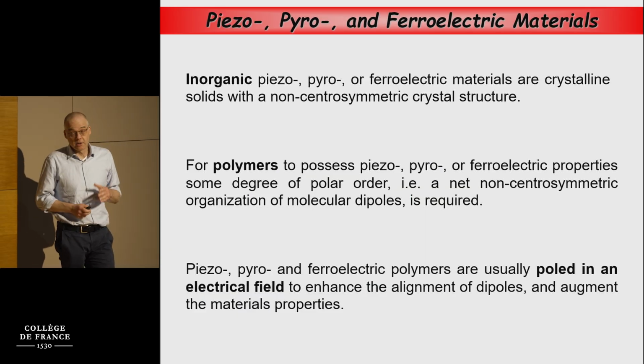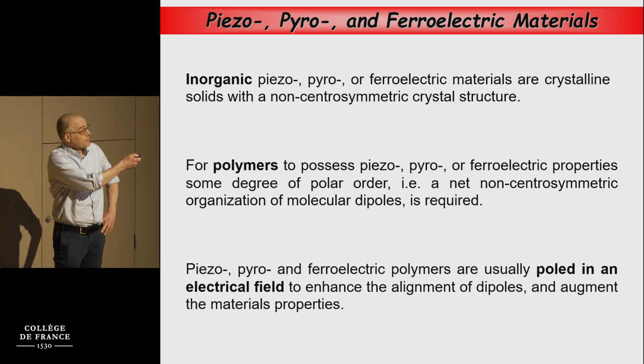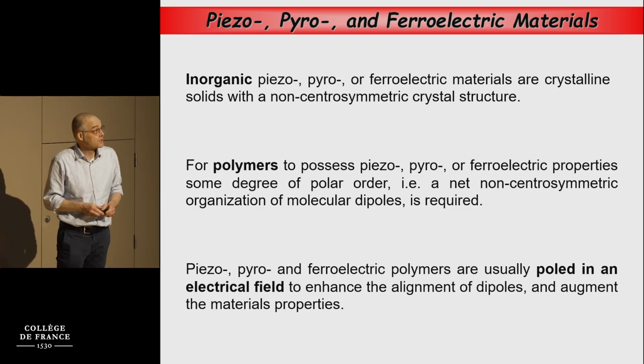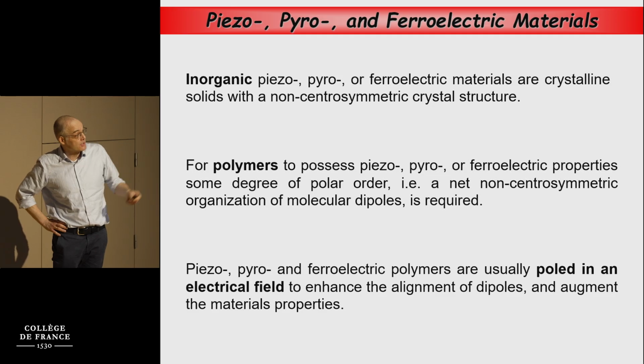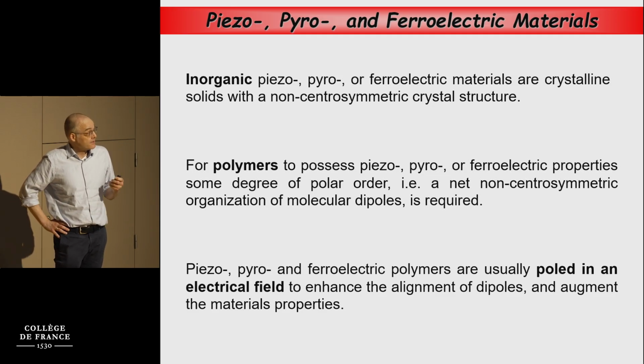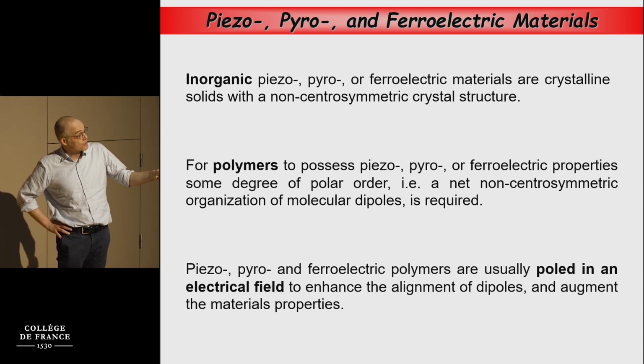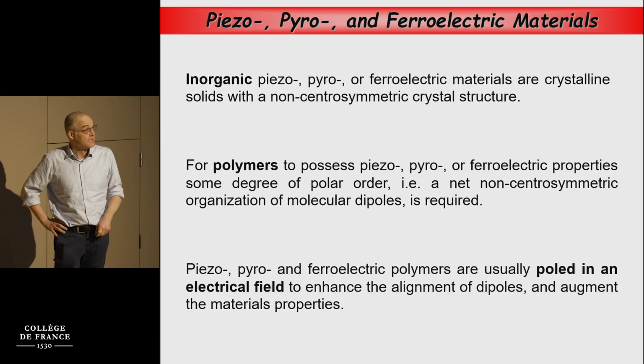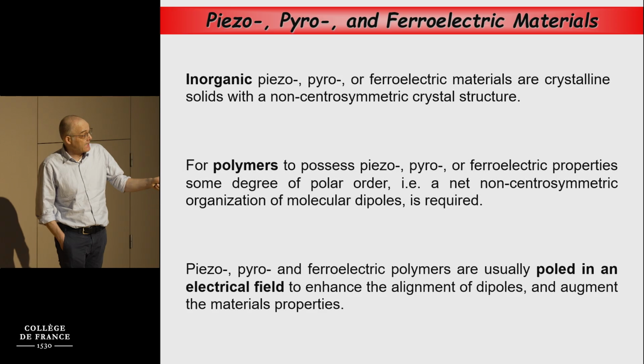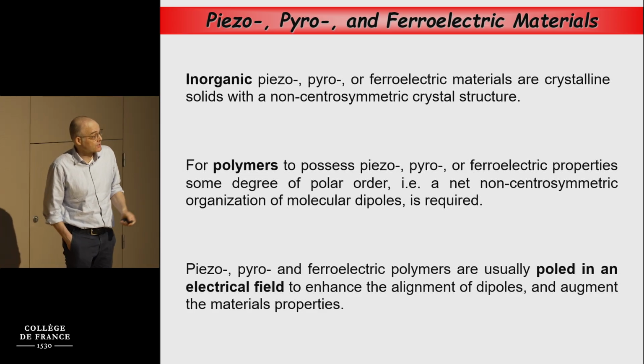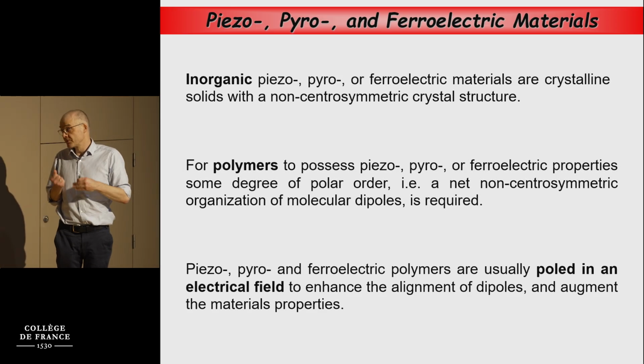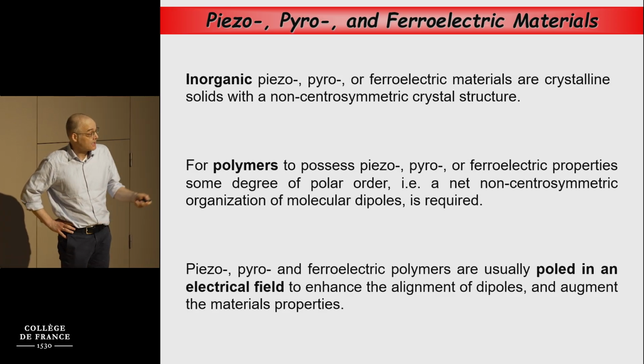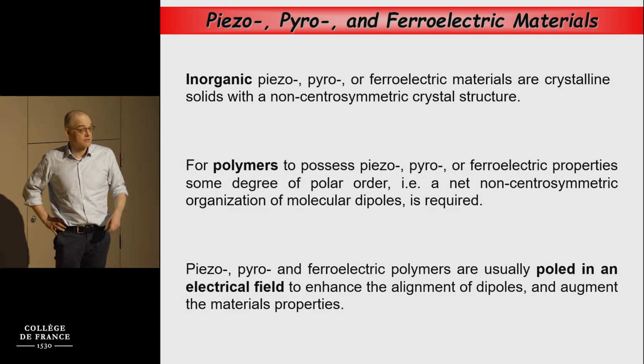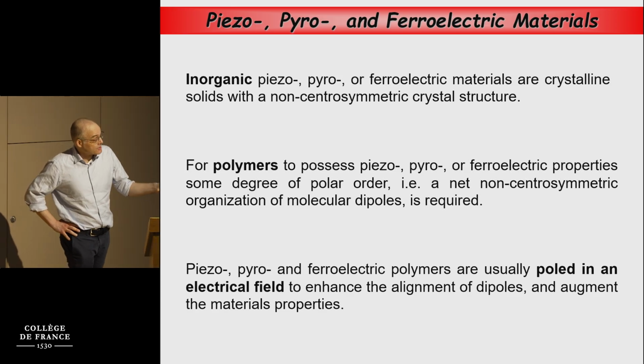So what's the challenge here from a polymer chemistry point of view? Inorganic piezo and pyroelectrics are typically crystalline solids, and they possess a non-centrosymmetric crystal structure. If we talk about polymers, this requires that these materials incorporate molecular dipoles, and we have to figure out ways to induce some sort of net polar order in these dipoles to generate an overall dipole moment. To achieve this, in most cases, piezo, pyroelectric and ferroelectric polymers are poled in an electrical field, sometimes utilizing mechanical stresses to enhance the alignment of dipoles and augment the materials' properties. This is the polymer challenge.